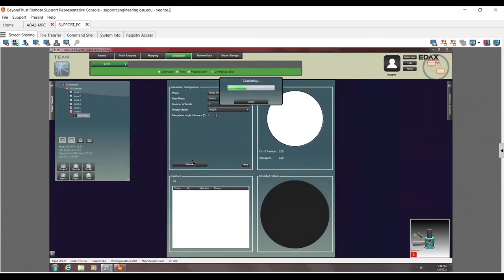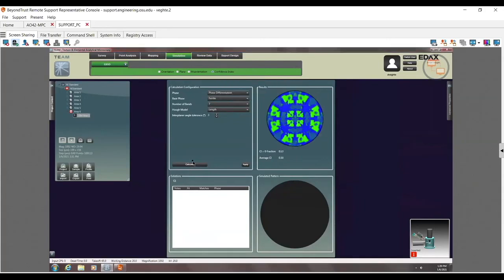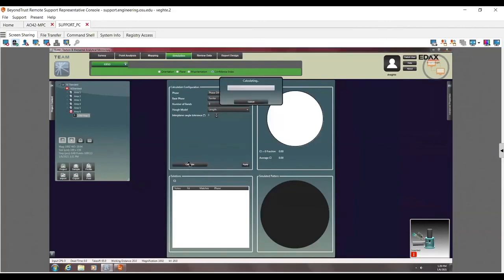And you can see it takes a little bit more. There you can see that there's a much larger percentage of area where it has a 0 fraction, in this case 0.13, and the average CI for everything is going to be 0.33. So again, this is a case where we have problems doing those 8 bands, and honestly, repeating this at 9 bands isn't probably going to make that big of a difference. Let's do this in 9 bands. It'll also take longer to do because it's more computationally heavy. So you can see this is taking much, much longer to do.